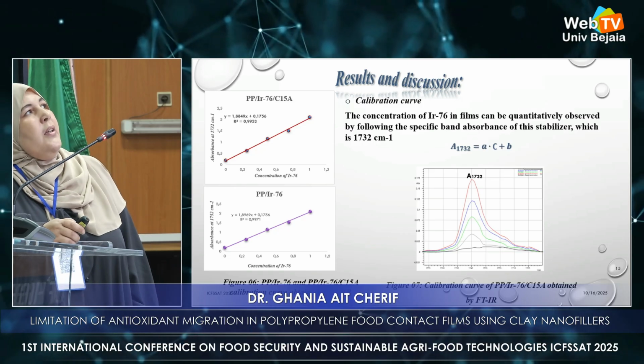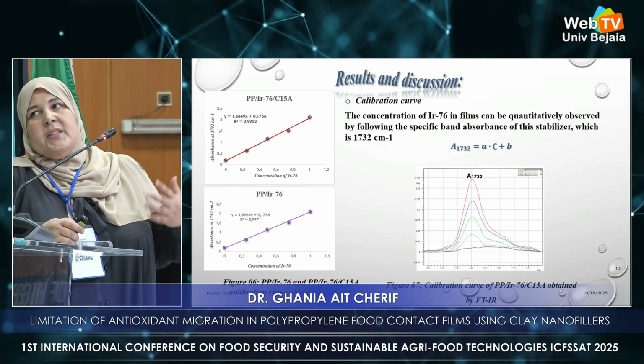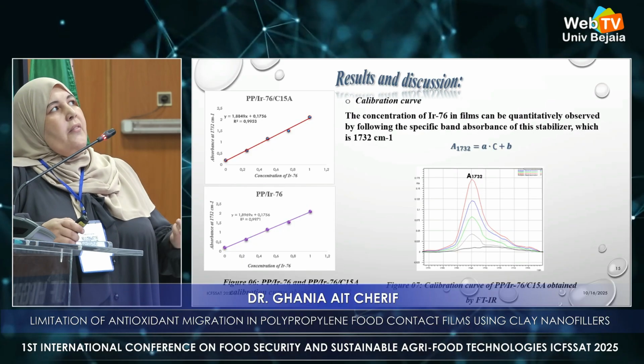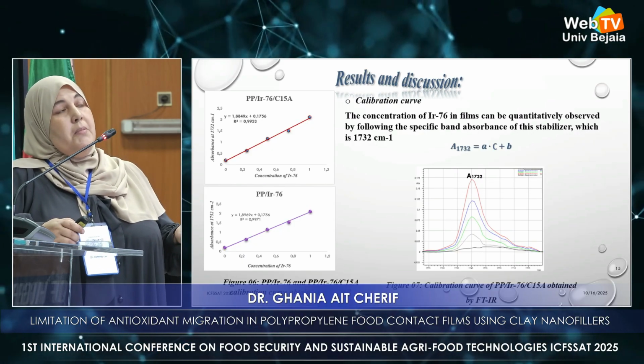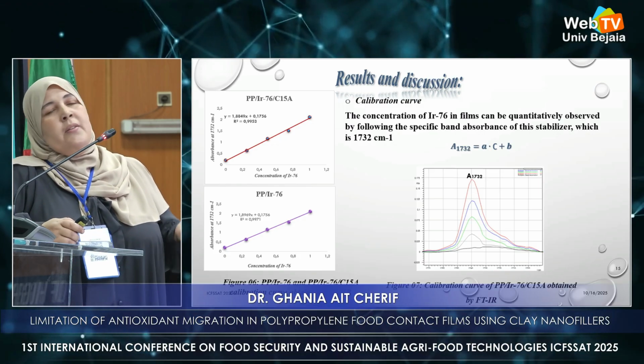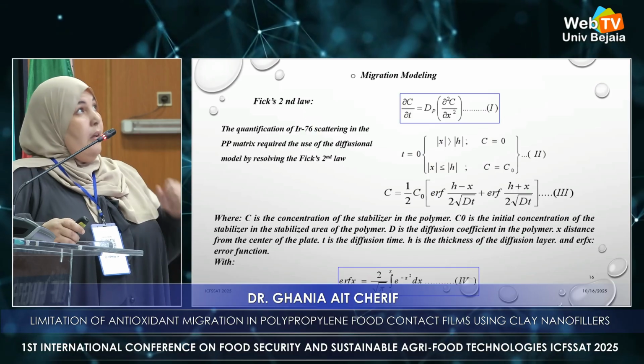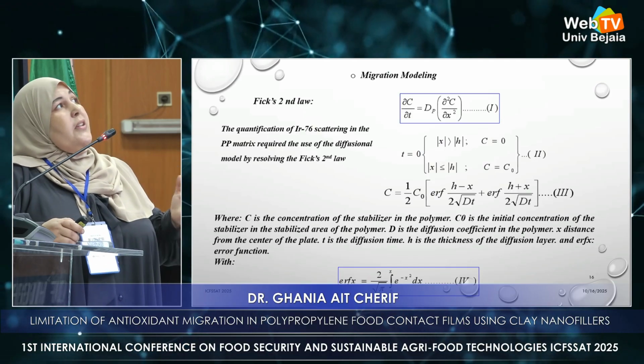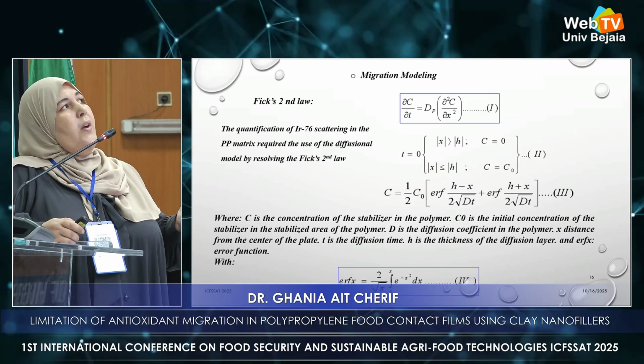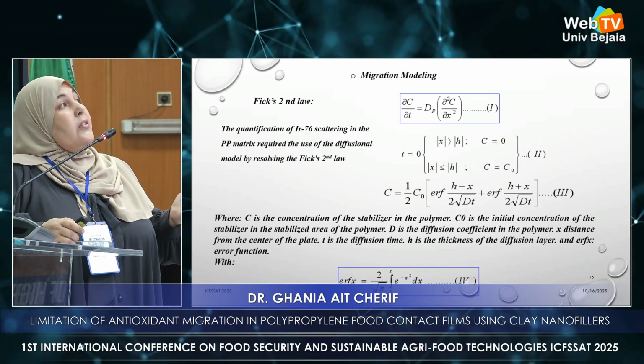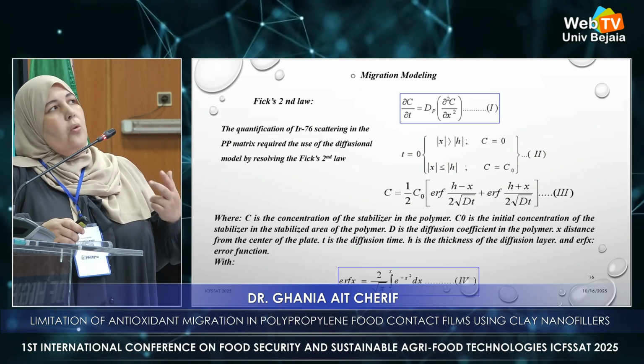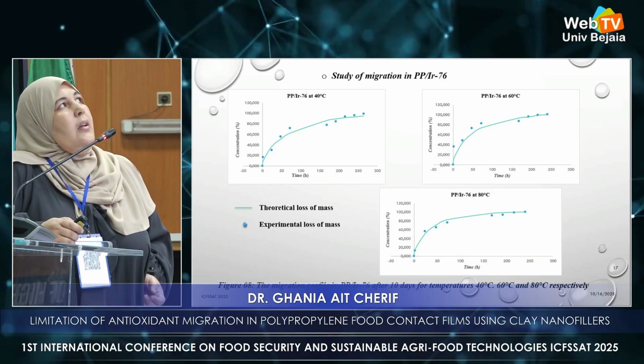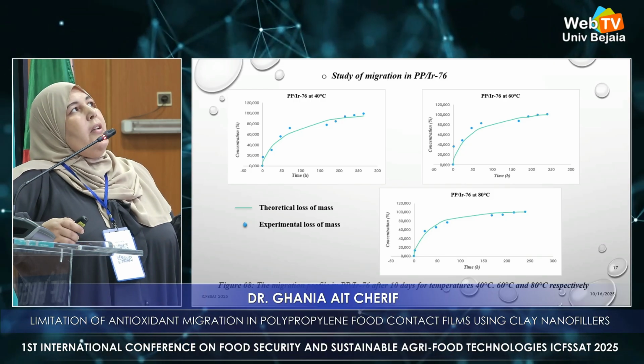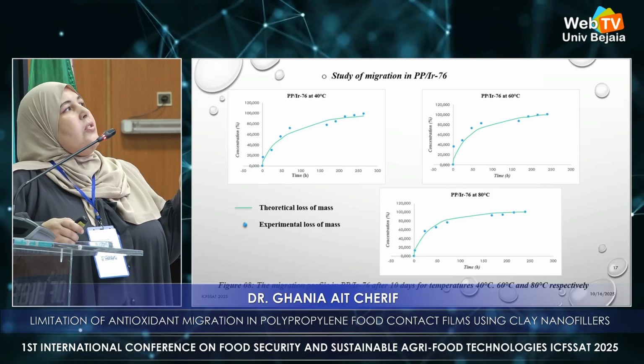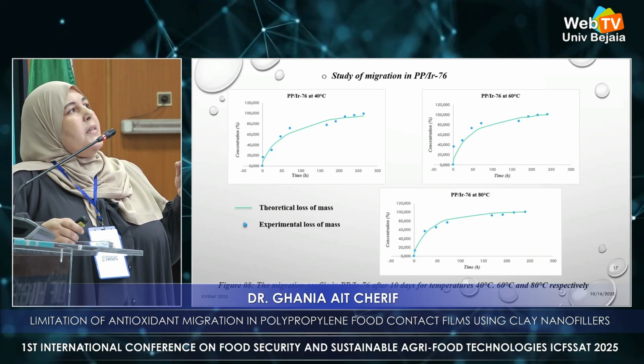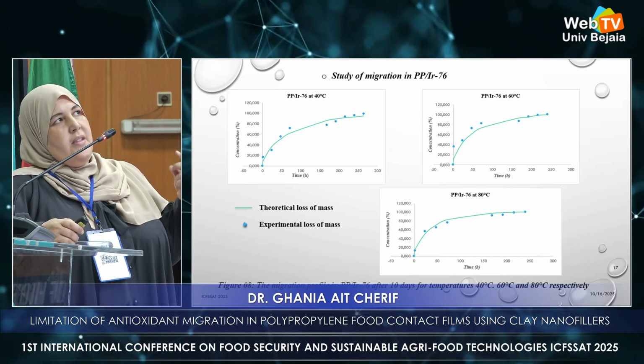The results. Calibration curve: the concentration of Irganox in each film can be quantitatively determined by following the specific absorbance band of the stabilizer, which is 1732 cm-1. The quantification of the Irganox diffusion in the PP matrix requires the use of different diffusional models by resolving Fick's second law. Here we have graphs illustrating the theoretical and experimental loss of mass versus time.